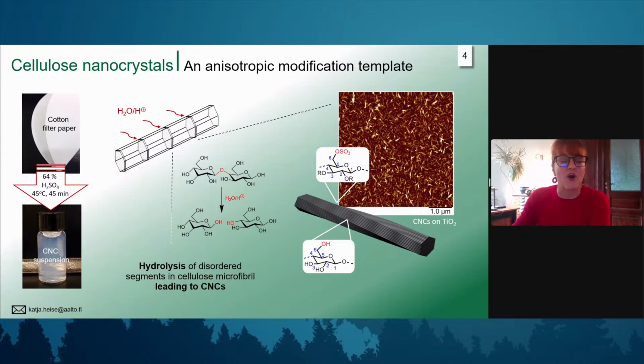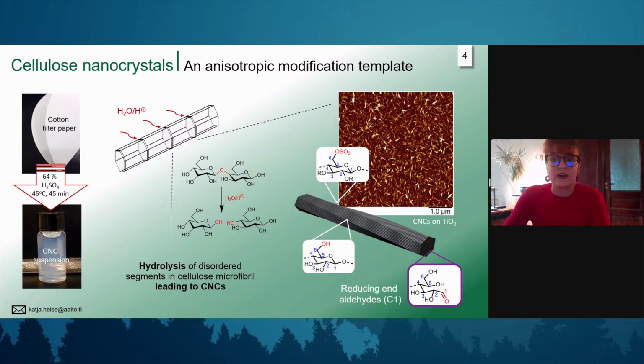As a consequence of the sulfuric acid hydrolysis, we have sulfuric acid half-ester groups on the surface. So we are essentially not working with pure cellulose, at least on the surface; we have a derivative. And we also have hydroxyl groups, of course, on the surface. And speaking about regioselective chemistry, there are also pathways for regioselective chemistry on OH groups. There are recent publications from Marco Beaumont from BOKU in Vienna. But what I was much more interested in, together with my collaborators, was to modify reducing end groups.